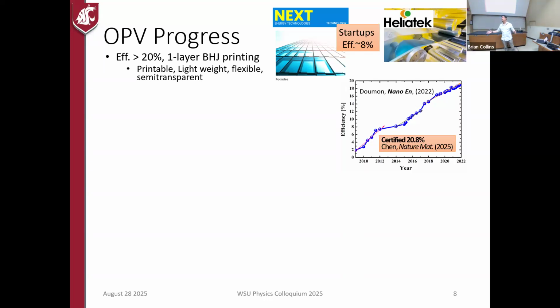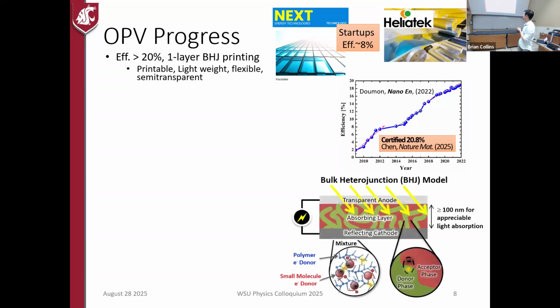square meter per minute is very real in this case, on almost like a Kodak film making apparatus. Actually, some of these startups originally started with a Kodak apparatus to print these things. The way that it works is you have a single layer printing of what you call a bulk heterojunction. So what is this? This is a mixture of an electron donor and electron acceptor molecule to create that PN junction you need for solar harvesting.